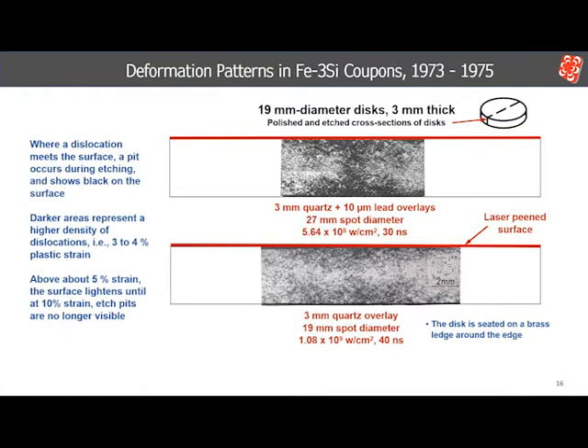The top figure is a disc shocked with the lead plus quartz overlay. The lead overlay was initially selected and used in these initial experiments because of its low vaporization energy, enabling more of the beam's energy to expand the vapor and increase the pressure. Lead worked very well for power densities between 0.5 and 1 gigawatt per centimeter squared, but its effect diminished at higher power densities. After this study, it was no longer used.